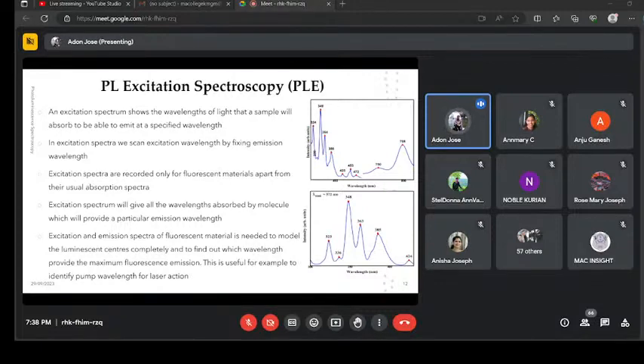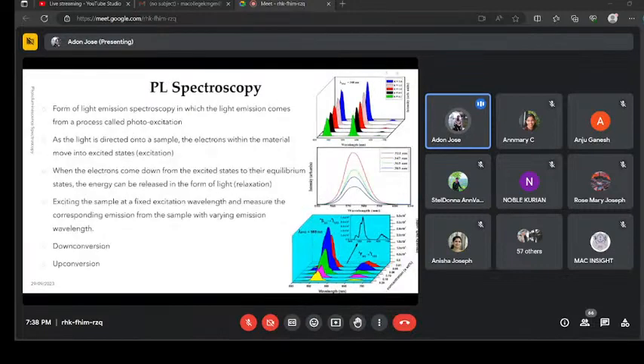So next we are going to PL spectroscopy, the photoluminescence spectroscopy. Actually, we can say photoluminescence is an emission spectrum. An emission spectrum usually describes the range of wavelengths of light emitted by a substance after it has been excited. So in fluorescence spectroscopy, usually the excitation monochromator is set to a specific wavelength known to excite the sample, that we have identified from the excitation spectrum, that is the excitation wavelength, and the emission monochromator is scanned through different wavelengths, which is the reverse of the photoluminescence excitation spectrum that we discussed in the previous slide.